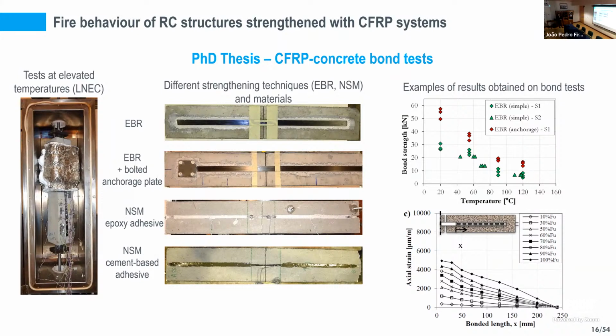And with this experimental campaign, we were able to provide new data to the literature at that time, with results about the bond strength reduction with temperature for all these configurations of strengthening systems, also providing new data regarding the stress distributions along the bonded length and how these stress distributions change with temperature and how they change across the different materials.